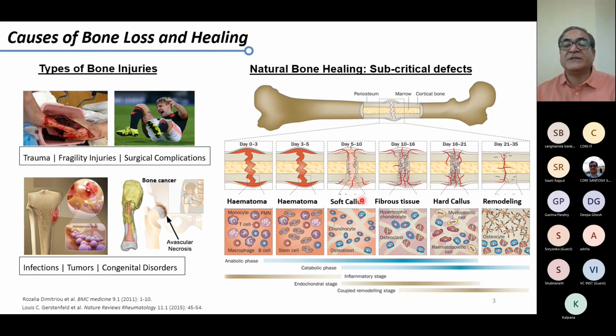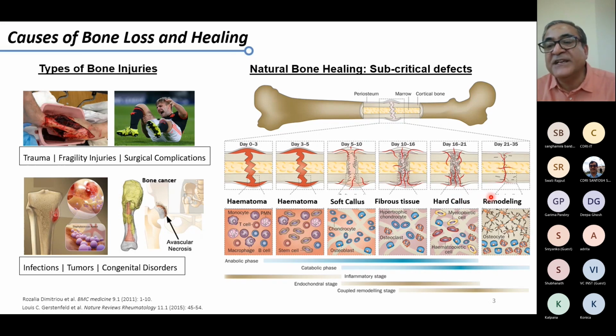So you get a soft callus formation, where chondrocytes and osteoblasts get differentiated from stem cells. Then you move into the fibrous tissue, and you get more of these cells, which harden the bone. At the same time, catabolic events start coming in. We are talking about a timeline of 10 to 15 days, when you will see the catabolic phase coming in. This continues until 3 weeks, where the hard callus is developed, and then finally at about 35 days remodeling happens. But what I have been trying to explain here is what the bone does on its own in a normal situation.